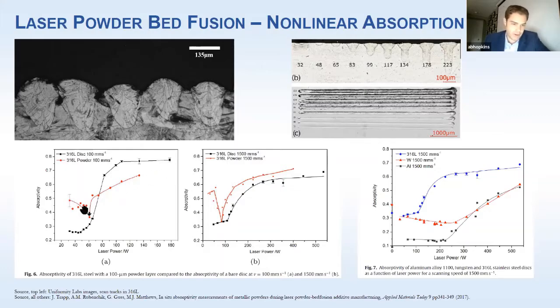And then there's a crossover point here. That's at very, very high energy intensities relative to the laser process. When you're actually running the laser, you're more in this regime here, the early regime. So if you take a look at this middle track, that's a more common laser powder bed fusion position. You actually have more absorption for 316L powder than you do for just a substrate because of the absorptivity of the powder. But with that said, you can see they track a little more closely when you're in this regime where you would normally print.